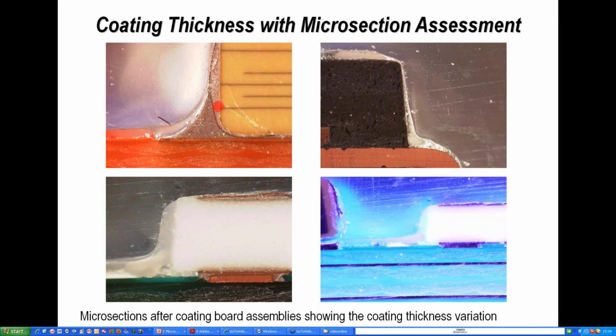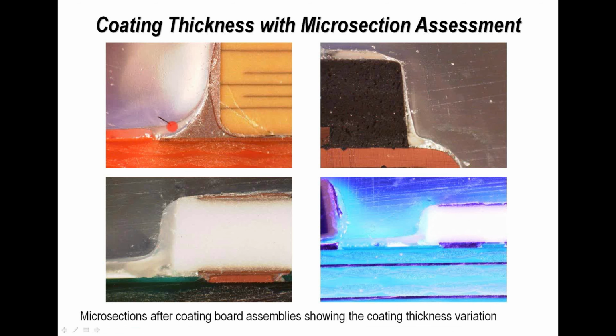If we just have a quick look, here you can see that the coating varies quite a bit. On the surface of the board, the coating is quite thick, and as we go up the side of this capacitor on the photograph, on the left-hand view of the screen, you can see quite a variation in thickness. If we move over to the photograph on the right-hand side at the top of the screen, the coating again varies quite a bit in terms of thickness, and right on the edge of the plastic device where there is a sharp corner, you can see the coating is quite thin. This is typical of all conformal coating processes.